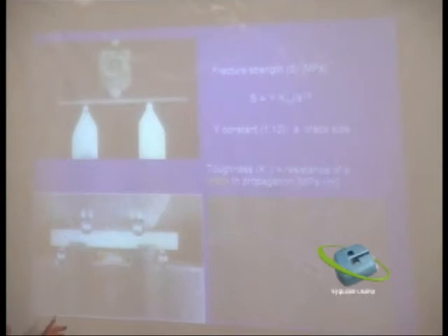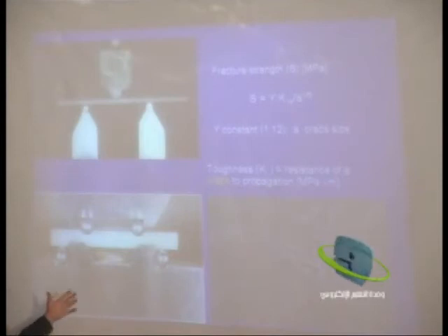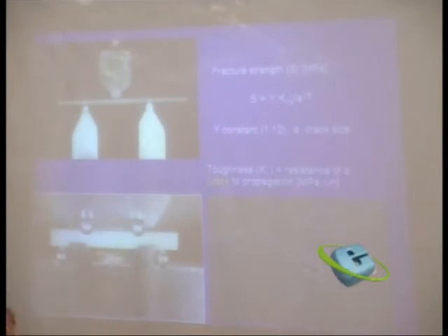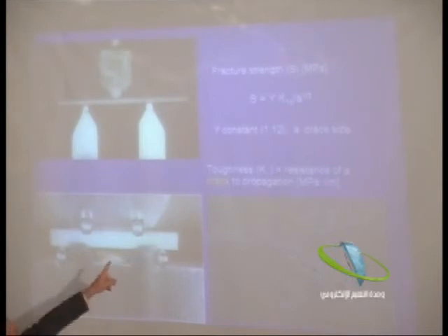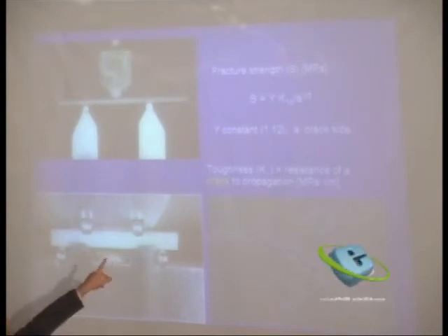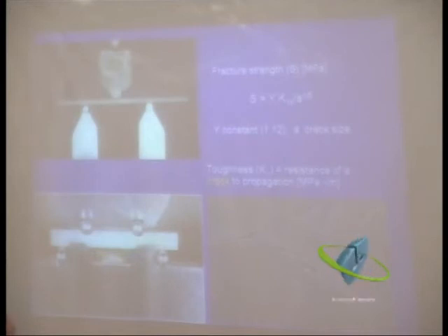So the way we measure fracture toughness is typically, as in here, where we put a small notch in the material, we load that material up, and we cause it to crack. So this fracture toughness, or K1C, is a much more fundamental basis, and this is why the strength of the material changes. The toughness stays constant, but because the defect size, or the crack size, this value of a in that top equation, is different, because of the different treatments, different porosities, etc., then this will influence the strength of